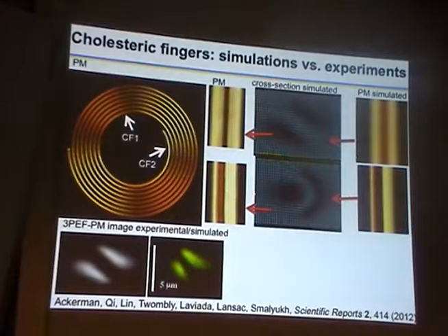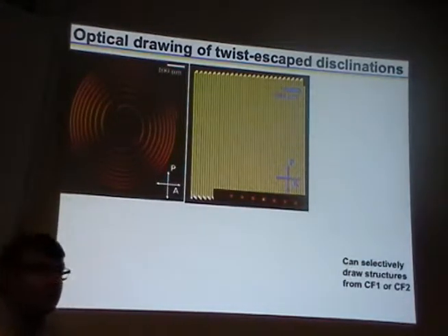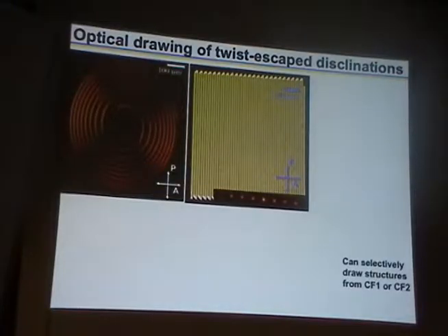Likewise, we can do it for the second structure of cholesteric finger second type. So you can see the appearance and polarizing microscopy texture is slightly different. It now became asymmetric, right? And so again, we can computer simulate vertical cross sections. They too are now resembling each other but different from what we had for the previous structure. And so this shows that we indeed deal with those particular director field configurations that I showed on the previous slides.